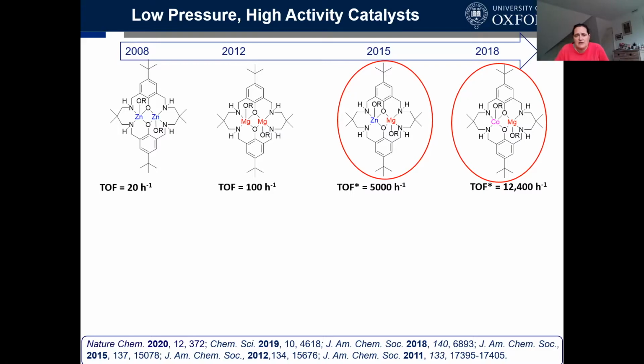Then later we began to look at other metals, and later still in 2015, we became interested in mixing two different metals, and we saw something quite interesting: when you put zinc and magnesium in this scaffold, you see an enhancement of activity that's really significant compared to either of the homodinuclear complexes. So zinc magnesium as a complex is much more active than zinc zinc or magnesium magnesium. From about 2018, we began exploring other metals. Today I'm going to talk to you about cobalt and magnesium together in this macrocycle scaffold and what we've learned.